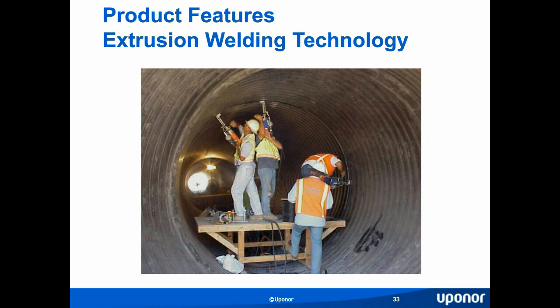Also, in addition to our internal welder, we can weld this pipe using our handheld extrusion welding technology. This is the technology that we used before we had the internal welder, and it's also used on lower pressure applications. We just finished a project in Oregon whereby the welding was being conducted on a pressure pipe running at 7.5 psi, and we were able to accomplish that with just our ID welds, as you're seeing here. We did not need the extrusion welder. The advantage, if you can use extrusion welding technology, is that there are thousands of these guns available throughout North America, whereas the availability of the internal welder is quite limited to the number of machines that we have.